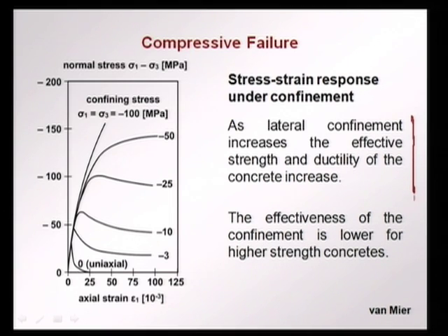However, we should keep in mind that this effectiveness of the confinement is lower for higher strength concretes. Why? Because higher strength concrete will have less cracking, and in the pre-peak we saw that higher strength concrete had a relatively larger linear range, and therefore less cracking develops, and if there is less cracking, there is going to be less lateral expansion, and the effect of the confinement comes in only when the concrete is prone to lateral expansion under high stresses. So, in higher strength concretes, the effectiveness of confinement, either active or passive through reinforcement, is less than in lower strength concretes.